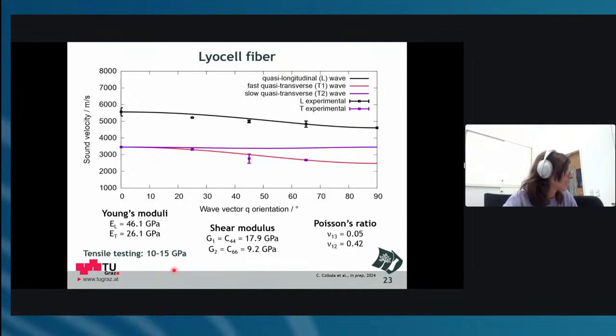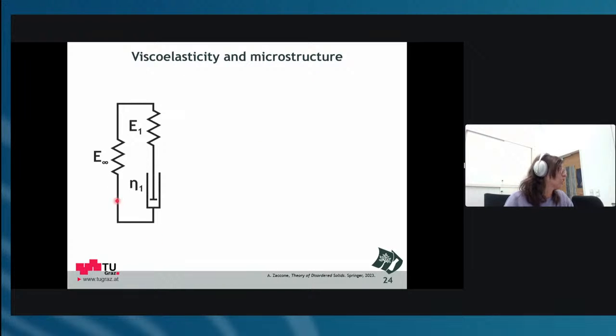Yes, and the reason why there could be such a difference is, I think, there are maybe two explanations that we have now, and they are pretty similar. You can look at it from a viscoelastic point of view. If you consider your fiber as viscoelastic, we used to describe that a lot with these spring-dashpot models. So the elastic part is described by the spring, and the viscous part by the dashpot. Now you apply a slow force. All your elements have time to react, also your dashpot. But if you now go into a high frequency regime, as in Brillouin, where we measure in the gigahertz, this dashpot is likely to not have enough time to react. So everything will depend just on the springs, and you kind of cancel or inhibit your viscous deformation.